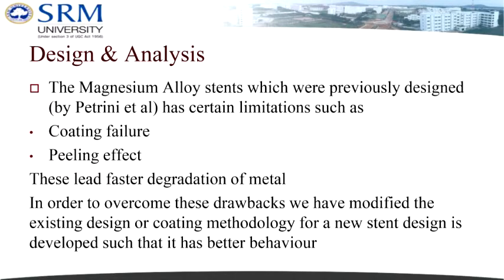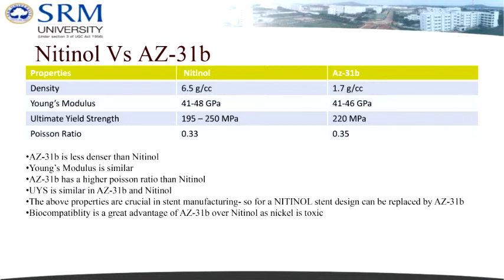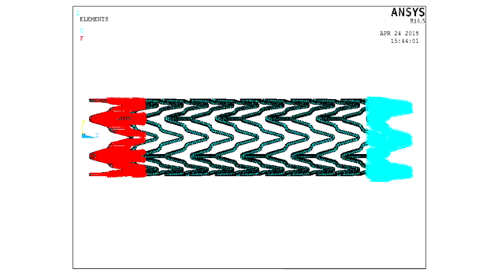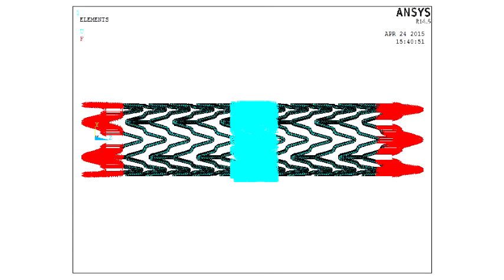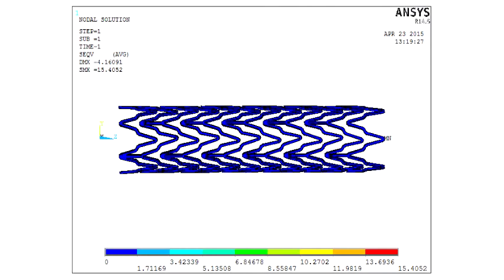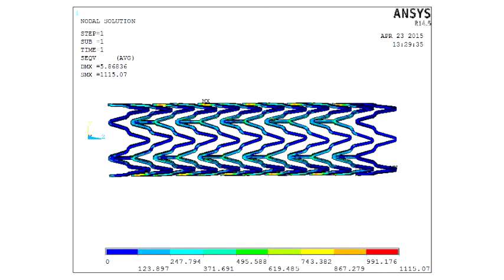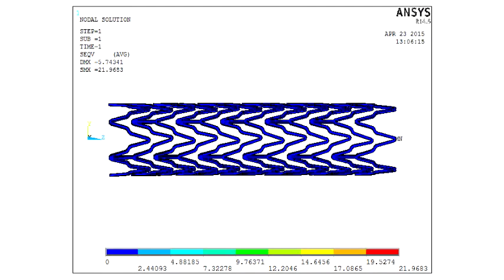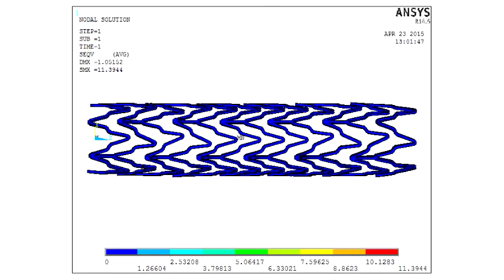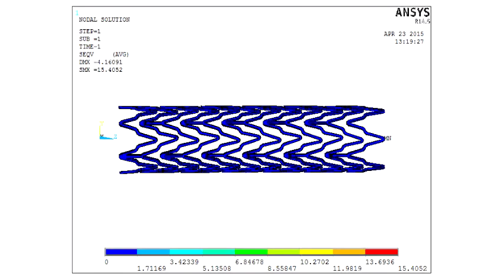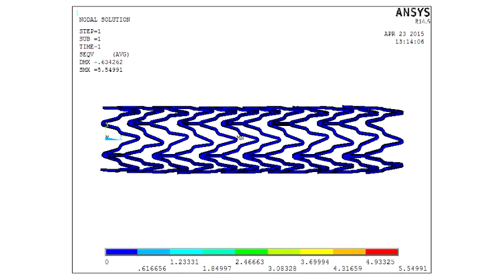Then, finally going for the simulation model using ANSYS software, we chose the nitinol stent model. The nitinol stent model has been chosen because the Poisson ratio as well as the density and the properties of tensile stress and the Young's modulus are similar to that of the magnesium alloy that we have chosen. In the ANSYS model, we took both the coated and treated metal properties as well as the bare metal properties, and while applying 5 Newton and 10 Newton loads, the coated and treated metal property has shown significantly low stress when compared to the bare metal, and this shows that our stent material that we have synthesized is completely compatible for a stent design, especially that of nitinol.